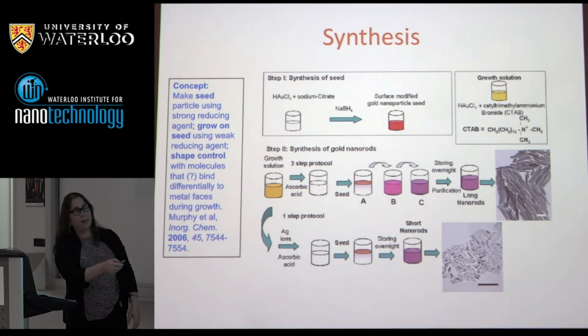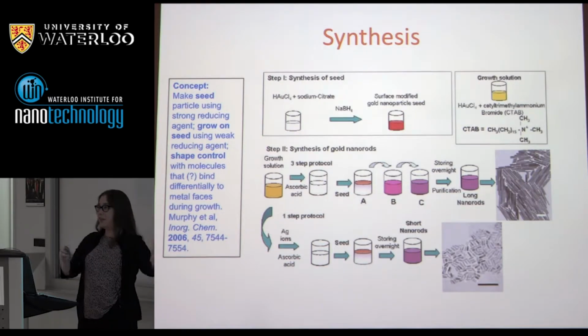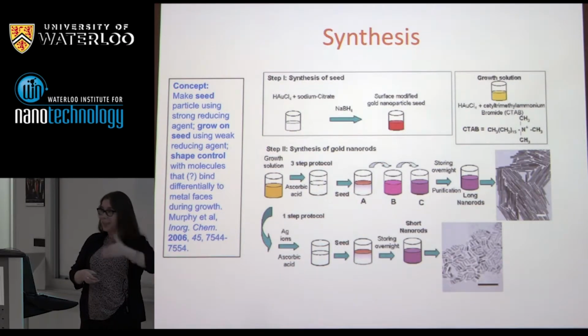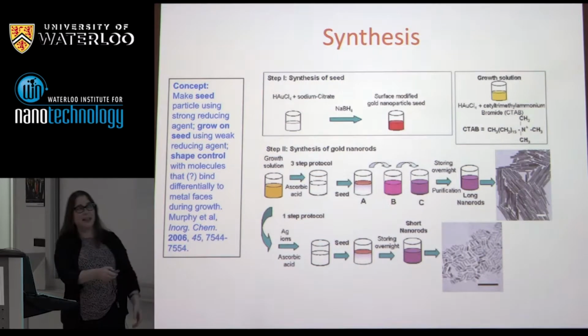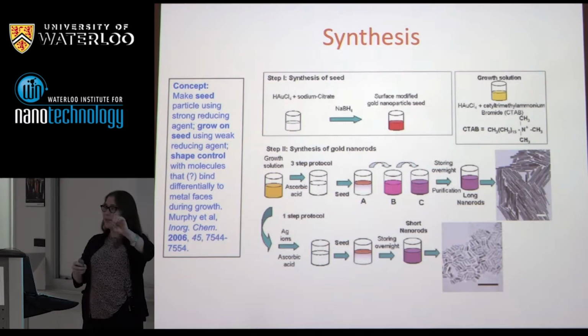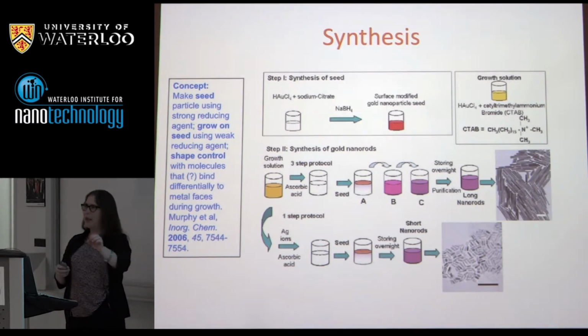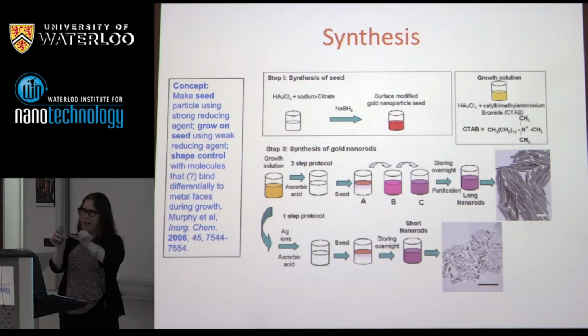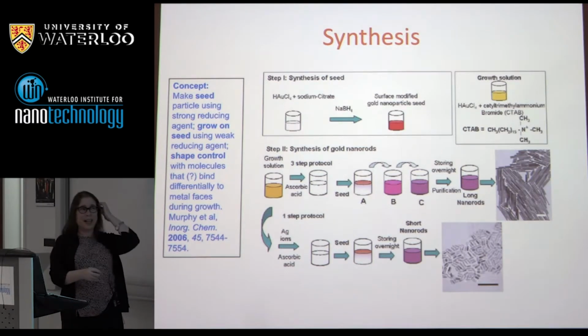You go from gold-3 to gold-1, there's a color change there. You add your seeds, and now in this pot, a whole bunch of colors start changing, which is telling you you're growing in like 30 seconds. Okay, things are growing pretty fast. You have multiple growth pots sped up, and so you go from 1 aliquot to here, 1 aliquot out, 30 seconds here, etc. And if you go all the way for gold, you can make these nice long rods, which are about 600 nanometers long and 20 nanometers wide, which is sort of like 2 tobacco mosaic viruses end to end. Now, this sounds great, right?